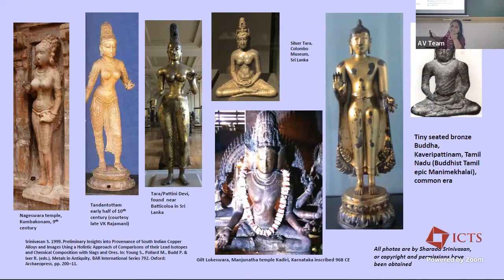And so if you have a lot of lead, the lead will also start oozing out to the surface. So that's why it's better to use a copper alloy and do the mercury gilding. So this is a gilded Nagapattinam bronze. And this fitted the late Chola period, the trace element and fingerprinting trends that I talked about.